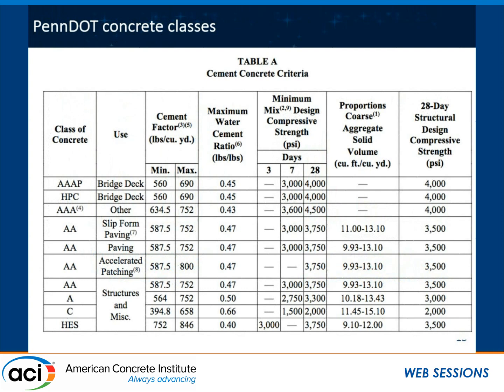Before I spend more time on this, let me introduce some of these concrete classes that PennDOT uses. We're looking at only these three rows, AAAP, HPC, and AAA. You can see over here that the structural design strength of all three of them is 4,000 psi. So the amount of strength that we need from a structural engineering standpoint is the same. However, the PennDOT specification requires AAA to be over-designed by at least 500 psi, so this is designed at 4,500. And the maximum water-to-cement ratio is 0.43 as opposed to the other ones that are 0.45. There's also some information about the minimum and maximum cement content in the PennDOT specification.